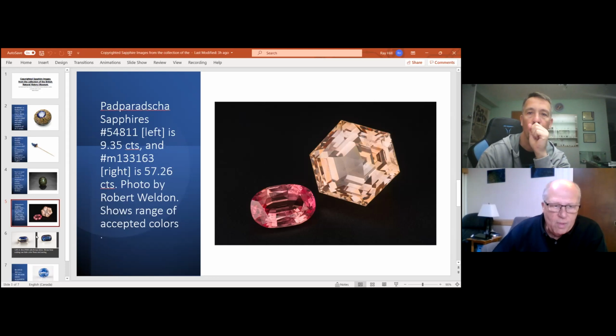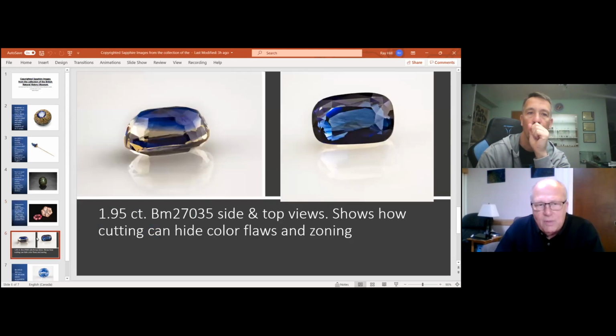The next shot I think is interesting because this is showing what I was asking Dick about, the sort of tricks of the trade that are done when you're cutting. And so you can see this stone has transparent blue and yellow zones in it on the side, but from the top, it looks like a predominantly almost electric iron blue stone, and the color looks relatively evenly saturated. Although you can see a slight hint through the table of a yellowish brown culet, I just think that this is one of the things that you really have to be careful of when you're buying stones. If you're hoping to get an evenly saturated stone, it isn't always what it appears to be when you look at it from the top.